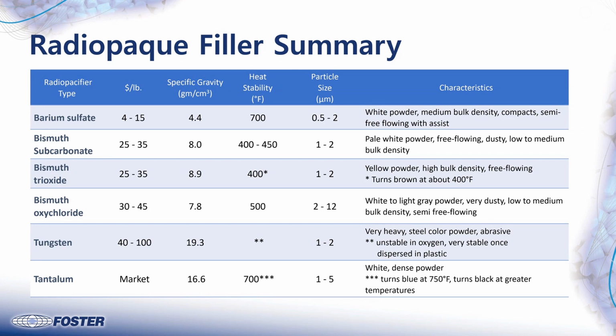So bismuth subcarbonate is probably next on the list, a very common radiopaque filler, with more density than barium sulfate. You see this a lot in cardiovascular and neurovascular, mainly because these are thinner wall catheters, and you can get fairly high loadings because of the density of the bismuth. It's compatible with some of the polyurethanes, the aliphatics, not all the polyurethanes, compatible with nylons, polyethylenes, PEBAX, so it's used very commonly.